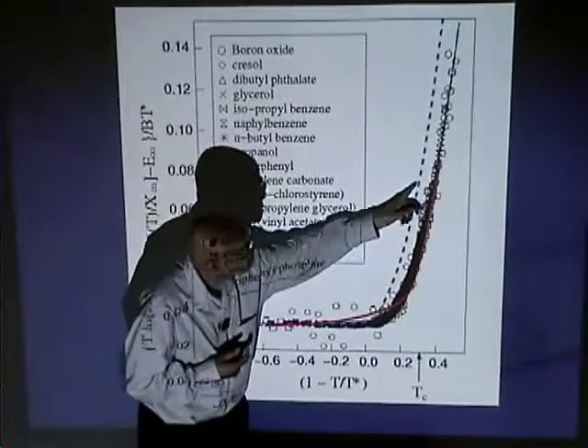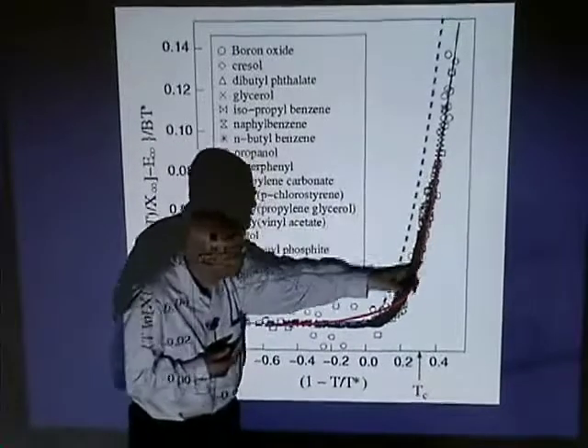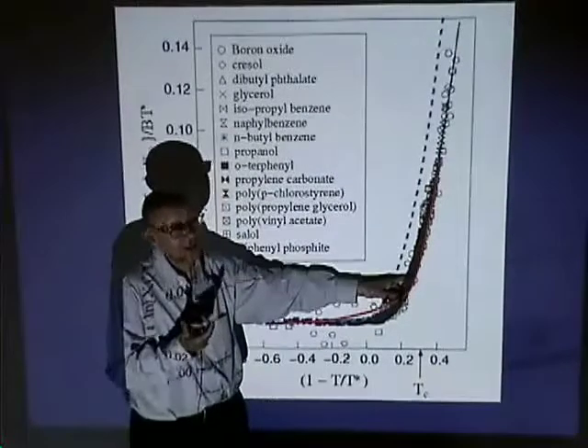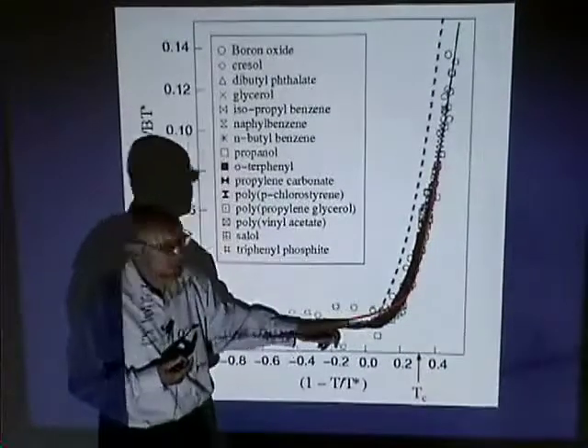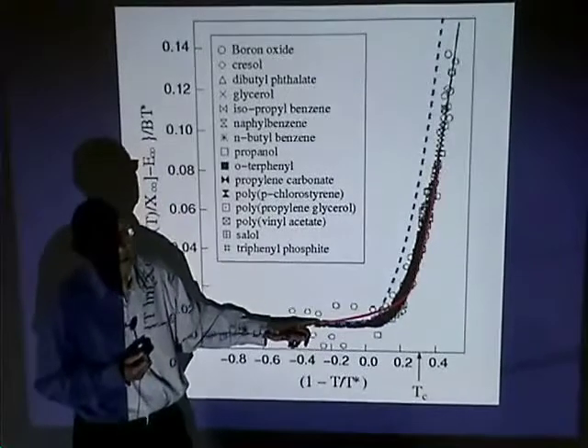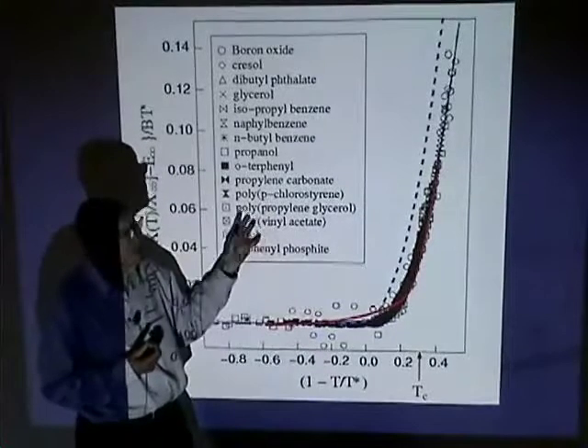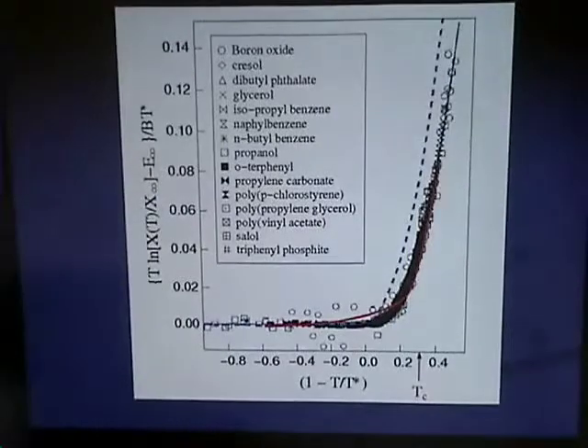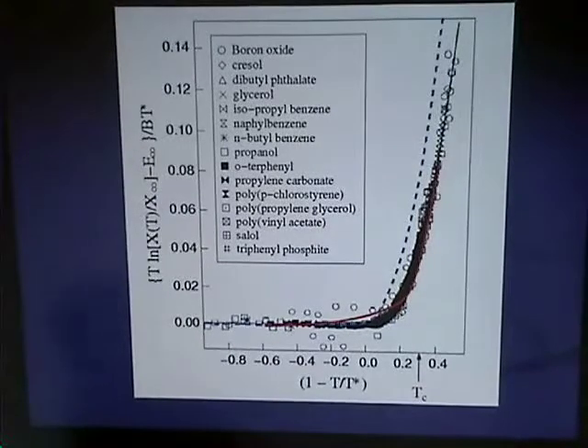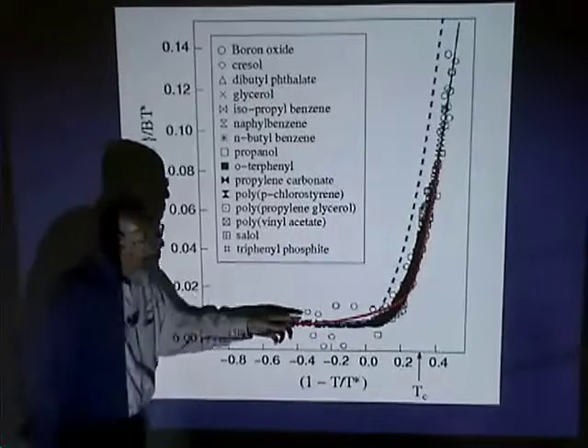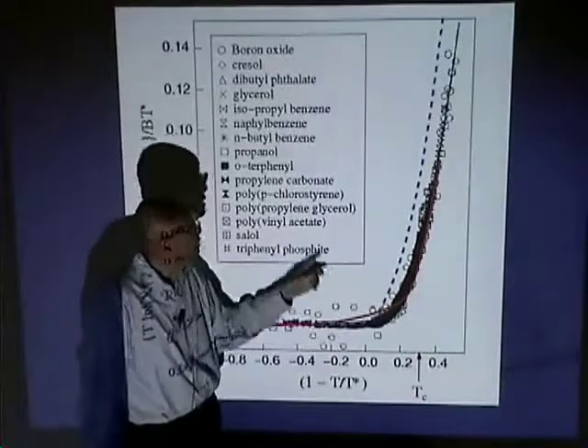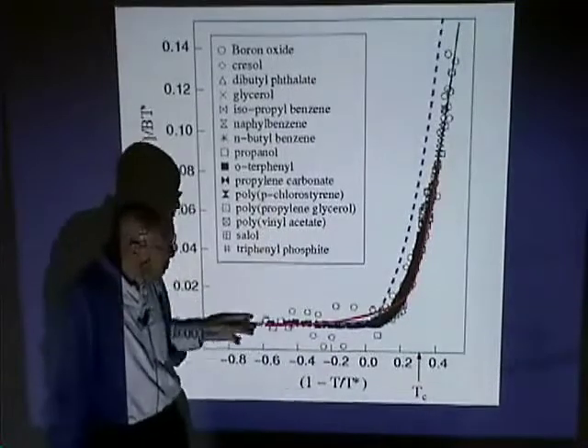Our calculation shows there's no consistent overestimate, whereas the Green-Kubo, the better calculation with the potential we can handle, is pretty much this curve. At this point I'll use this as sort of the most comprehensive test using all the data, keeping in mind that the potential binary Lennard-Jones isn't meant to fit any one of these. So all you can do is just look at the trend.